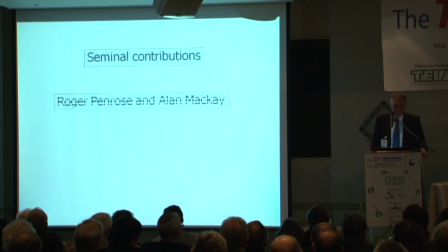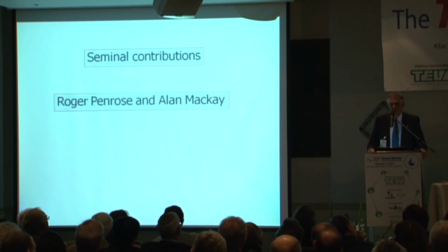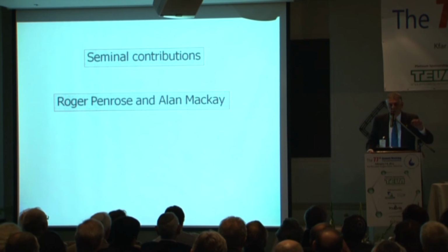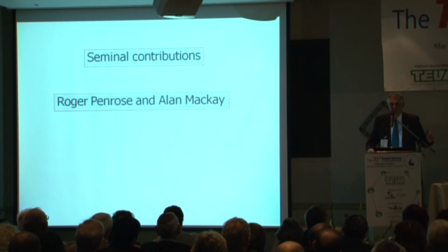Several people made a very seminal contribution: Roger Penrose and Alan McKay. Roger Penrose showed that you can tile a plane with two rhombi without gaps, one a thin rhombus, another a thick rhombus, and it had five-fold rotation symmetry and no repeating motif.